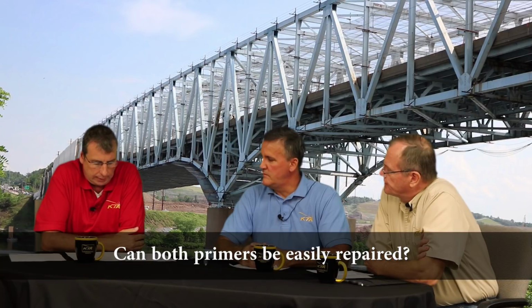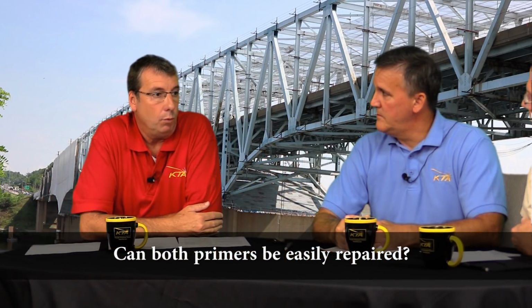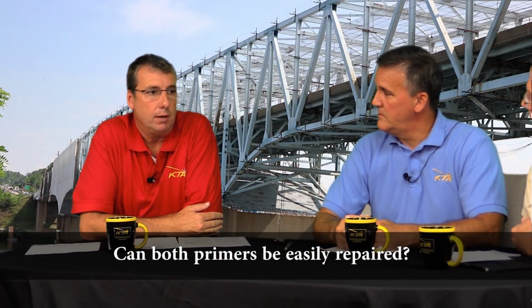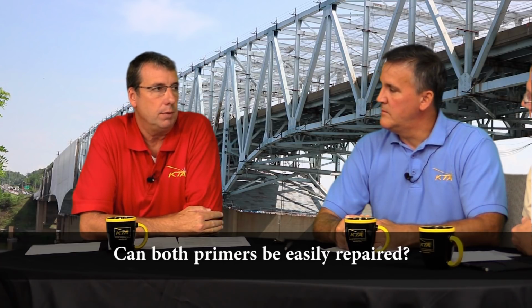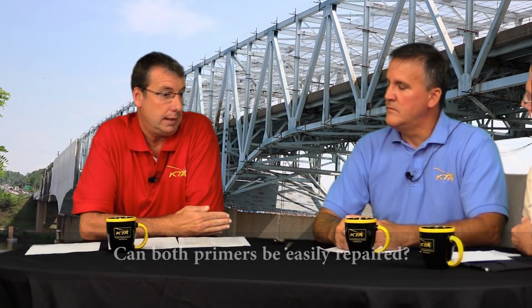Sure. For inorganic zincs, you can repair them with an inorganic zinc, but the initial application better be pretty green. In other words, it cannot be fully cured, and then you can do some touch-up with inorganic zinc. But if it has gone through a cure, I would highly recommend going with an organic zinc for repair of the materials. In either case, the inorganic zinc, whether it's a new application or repair application, they're spray materials. Very, very small areas can be touched up with a brush, but pretty much you're looking at a spray application.